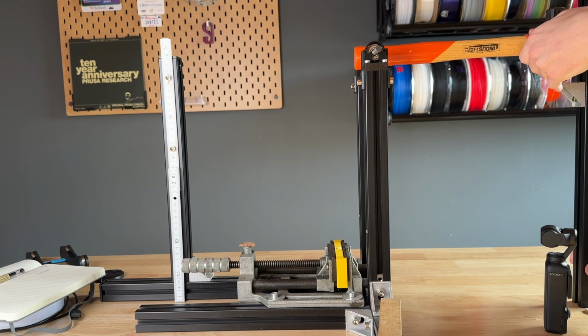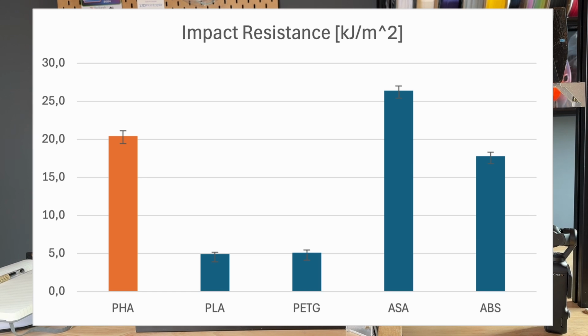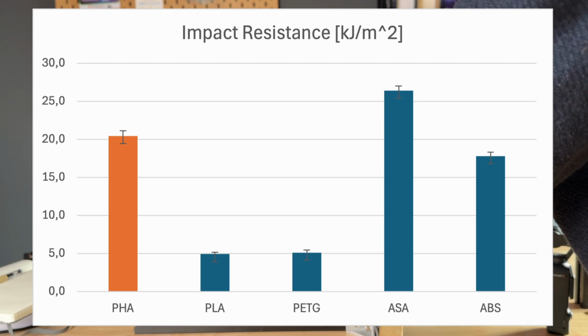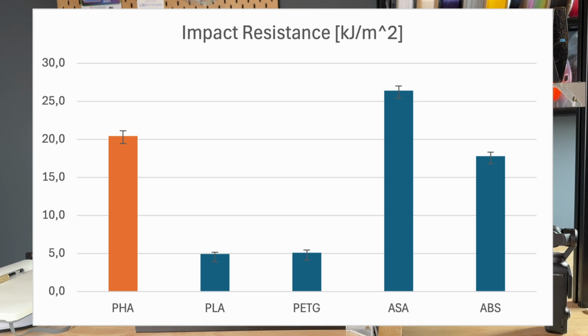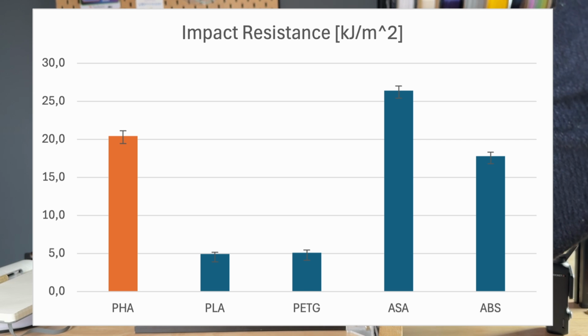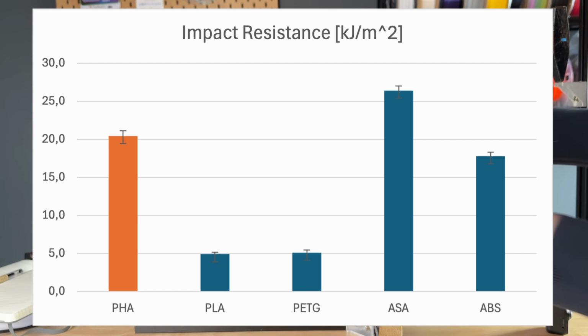The test shows that it has an impact resistance of about 20.4 kilojoules per square meter, according to my test, which is of course not an official testing device. PHA has 4 times higher impact resistance than regular PLA, which can be very helpful for some applications.